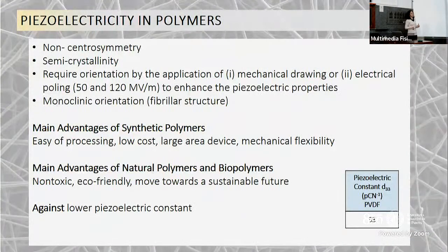So piezoelectricity in polymers and in natural materials can be achieved. There are some conditions that need to be fulfilled. So they are reported here. The material should be non-centrosymmetric. In most cases, it should be semi-crystalline. As we showed before, an orientation is required, and this orientation can be achieved by the application of an external mechanical stress, so it is called mechanical drawing, or also by the use of electrical poling, so applying to the material a very high electric field.